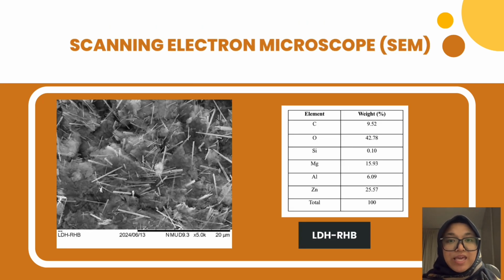Next, we examine the LDH with rice-husk biochar composite. The SEM image reveals fine crystalline LDH particles distributed across the rough surface of the rice-husk biochar. EDX analysis shows the successful integration of LDH onto the rice-husk biochar with the following composition: carbon 9.52%, oxygen 42.78%, silicon 0.10%, magnesium 15.93%, aluminium 6.09%, and zinc 25.57%. The rough surface and distributed particles indicate a strong interaction between LDH and rice-husk biochar, which enhances the composite absorption properties.